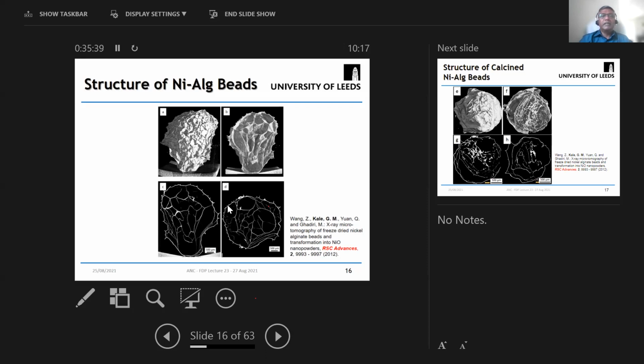So these two images, the first image on the left, A, is a freeze dried bead of nickel alginate. Sorry, these are freeze dried, so they are not dried at 80 degrees Celsius. So what you see here is the external structure of the bead in this particular micrograph. And you can see that there are indentations on the surface due to freeze drying or shrinkage of the bead itself. So originally they were spherical, but due to uneven shrinkage, the bead shape has been distorted and it has been indented.